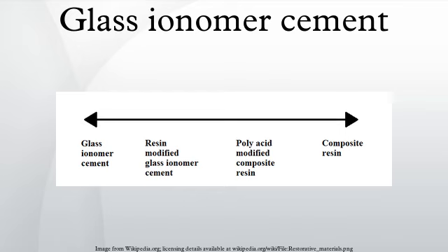For restorations placed in the primary dentition, no difference in the failure rate of single-surface GIC and conventional amalgam restorations after 1 and 2 years. A 32% lower failure rate of single-surface GIC restorations than that of conventional amalgam restorations after 3 years. No difference in the failure rate of multiple-surface GIC and conventional amalgam restorations placed in primary teeth, after 2 and 3 years.